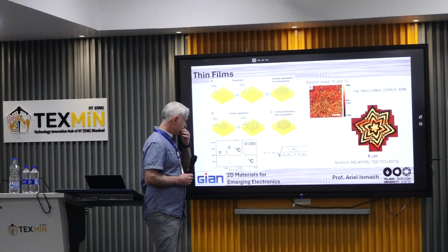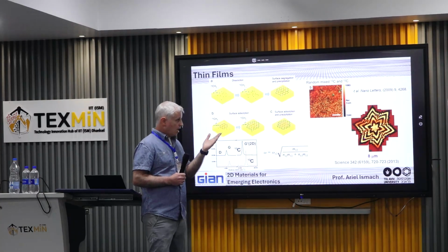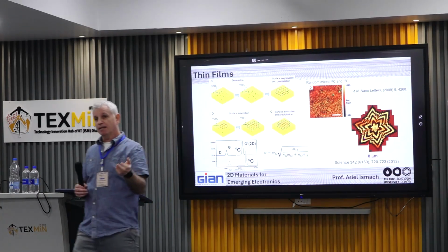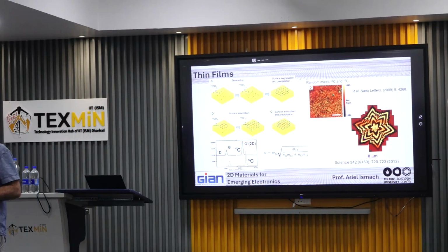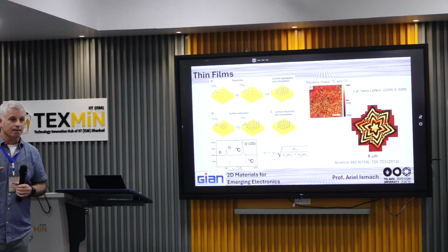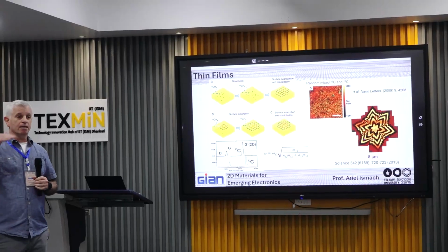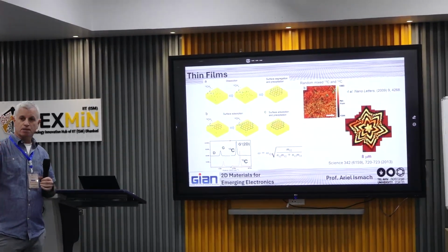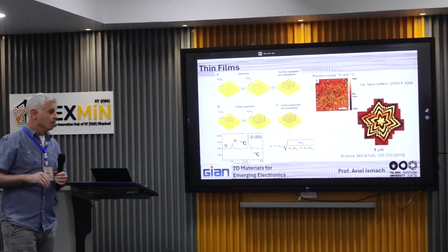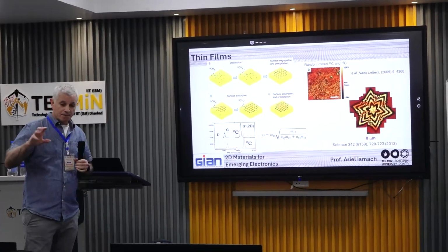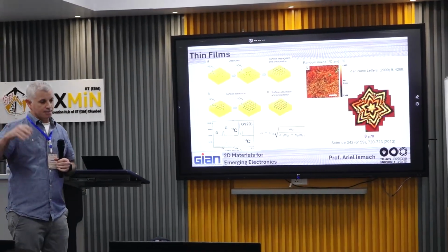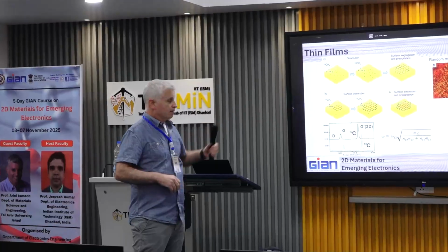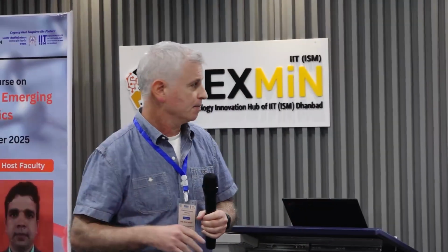Okay? And now, how is that helpful? They did this type of growth, this cycling. For nickel, they took the nickel and exposed it to methane at high temperature, but in this case they exposed the metal to, let's say, 5 minutes of C13, then closed it, and then 5 minutes of C12. I don't remember the time, it doesn't matter.